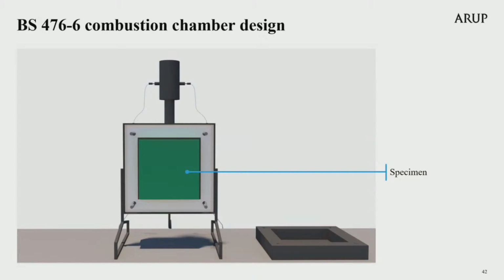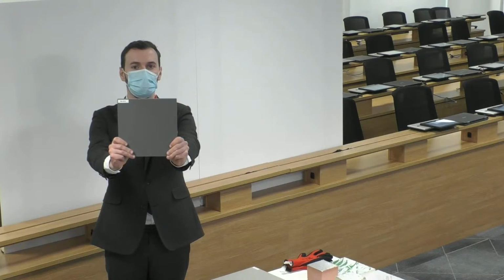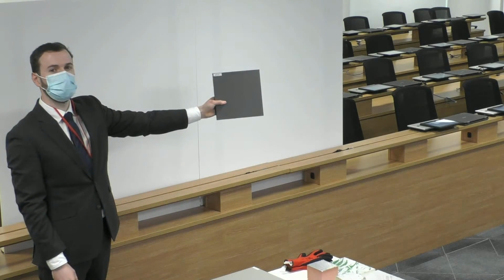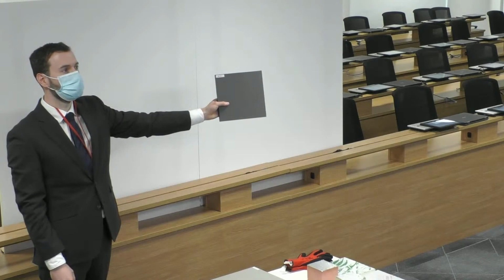The image on screen shows the specimen being held up in front of the opening to the combustion chamber. The opening to the combustion chamber recess is slightly smaller than the green specimen on the screen. Each specimen is square and measures 225 by 225, as I said. My colleague Tom is now holding up an example of the Part 6 specimen. Whilst the sample is of dimension 225 millimetres, the opening in the combustion chamber is 190 by 190 millimetres. The result of this is that a boundary around the edge of the sample is not directly exposed to the heat from the electric heaters and gas burner.